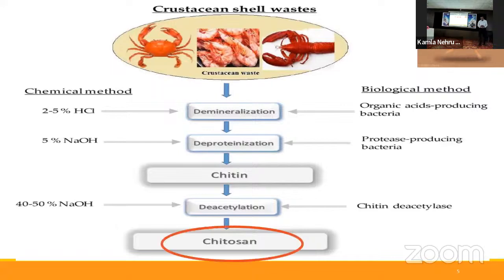We have worked on a compound called chitosan, which is derived from crustacean shell wastes. This crustacean shell waste is converted into chitosan by two methods. One is the chemical method by treatment with HCl, then NaOH, and then deacetylation to give chitosan from chitin. And the second method is a biological method where the harsh acids and bases are avoided. On the contrary, what we use are protease and enzymes, leading to formation of chitin, which is further deacetylated to give chitosan.